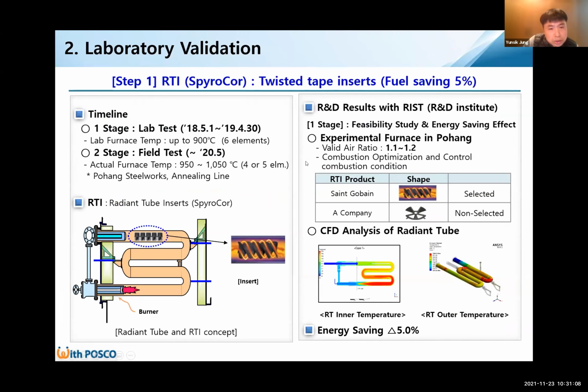Radiant tube inserts, so-called SpyroCor, are twisted tape inserts. They bring 5% fuel saving. Lab maximum furnace temperature was just set up to 900 Celsius degrees due to limited lab circumstances. It has 6 elements, but the field test was performed at actual furnace temperature. I will explain this result later.